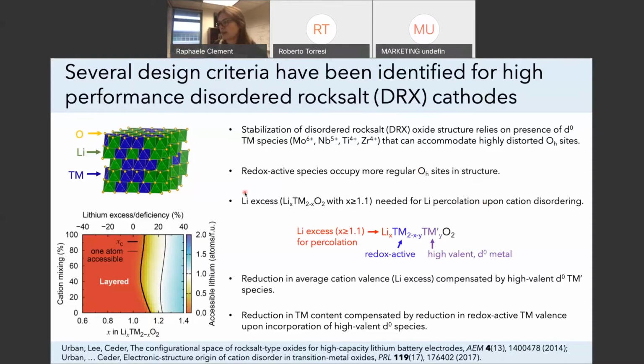So if we want to rewrite the general formula of these materials, we have lithium with some excess. We have a transition metal redox active species. We have a non-redox active transition metal species, which is here to stabilize the structure. It's usually a high valent d0 metal. And so what this shows us is that, first of all, we are reducing the average cation valence by having this excess lithium. But this cation valence reduction is compensated by the fact that we now have also high valent cations. So overall, we can keep charge balance by compensating the excess lithium by some high valent cation.